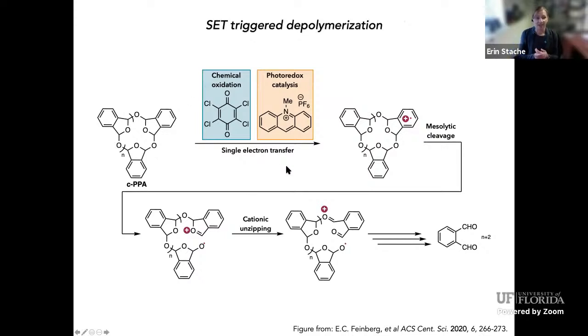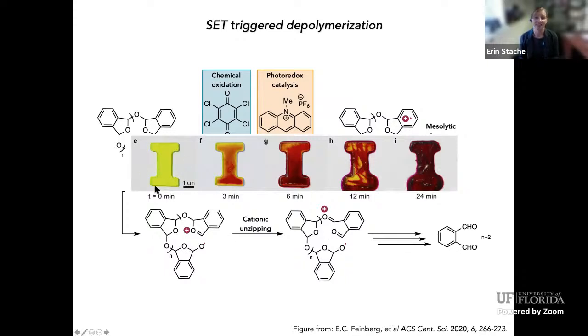And so they showed that they could take a film of the cyclic poly(phthalaldehyde) with this acridinium photocatalyst, which is very oxidizing, and in the presence of plasticizer, they could affect a single electron oxidation, and mesolytic cleavage will ultimately cationically unzip the polymer to give off monomer and destroy the polymer film. And so this is what the films look like. In just 24 minutes, they pretty much completely destroy them. This very pretty yellow neon color of the acridinium, and then it decomposes over time. The important thing to note here is that cyclic poly(phthalaldehyde) is not stable to UV irradiation. So if you leave it in sunlight, I don't want to give too much of a spoiler away, but it's not going to be stable. And in this case, when they're running these depolymerizations, they're using 370 nanometer LEDs.